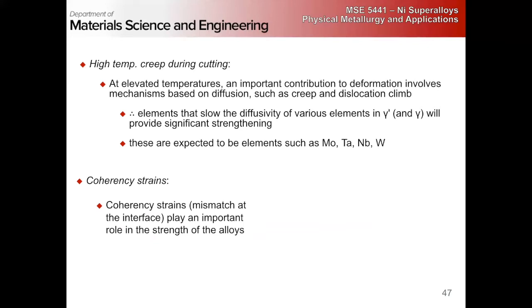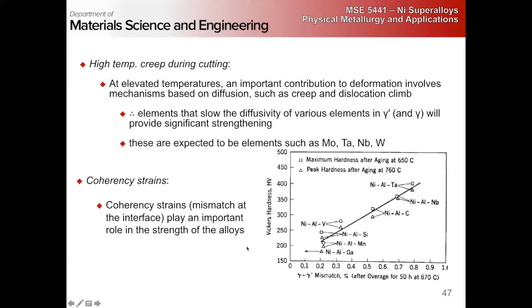During creep, we have to take diffusion-mediated mechanisms into account. So again, the heavy, slower diffusing, high melting point refractory metals are very good for providing additional strength against gamma climb. And then we also have to consider the effect of the coherency strain.